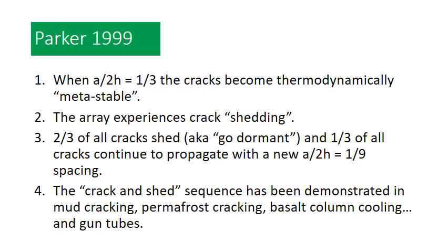And they'll go through a crack and shed sequence potentially several times as long as the stress is acting on those cracks and there's sufficient stress intensity to drive the cracks. Now, Parker's demonstrated that this particular sequence occurs in mud cracking, permafrost cracking, cooling of basalt columns, and he also demonstrated it in gun tubes.